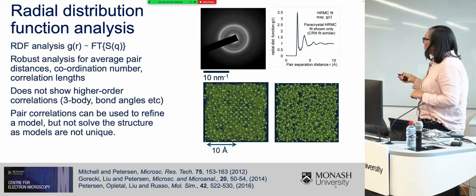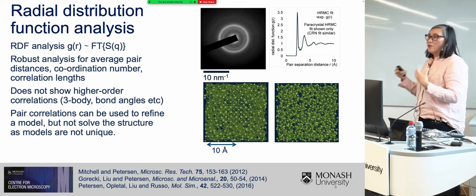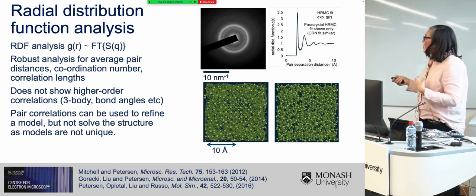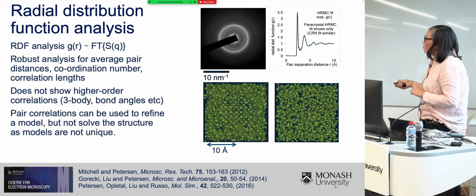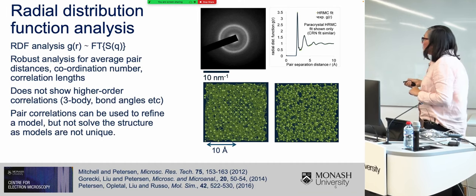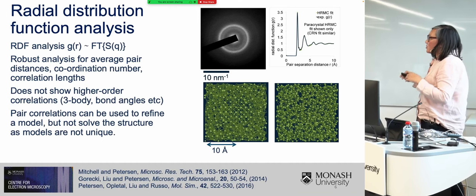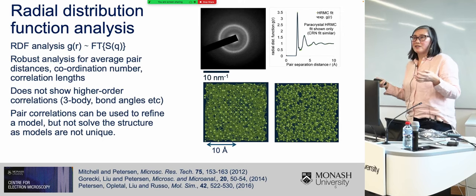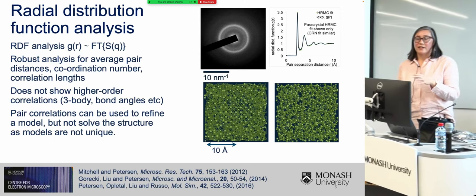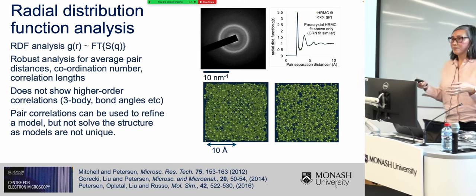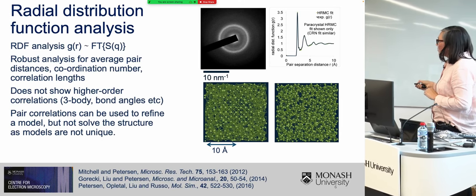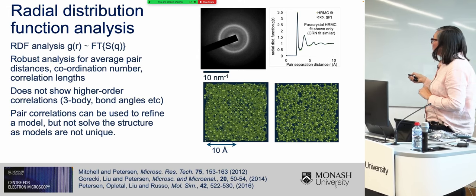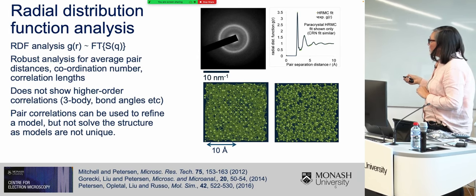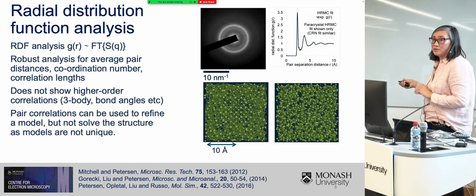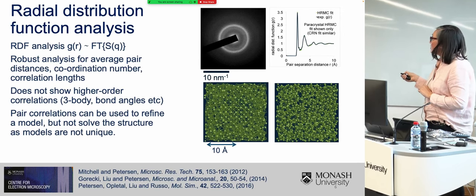However, this one-dimensional function does not show you the higher order atomic correlations. For example, it won't show you what the three body correlations are or the bond angles. And also, you cannot use this information to solve your structure, in the same sense that you use X-ray diffraction to solve a crystalline structure. So if you want to get particle level information from this pair distribution function, the best you can do is refine atomic models so that they're consistent with this RDF.